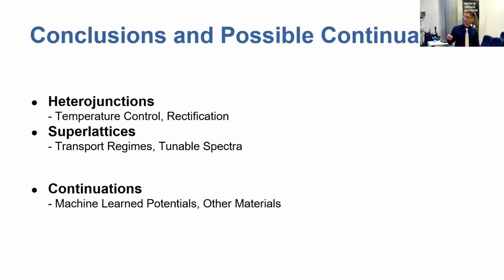Then we also described superlattices, which correspond to multiple interface structures. We have seen that in this case we can observe different phonon transport regimes, in particular the coherent phonon transport regime, which was not observed until superlattices became available. We can observe the coherent phonon transport regime only in superlattices, and we have also seen how superlattices provide us a viable means of tuning the phonon spectra of the material and controlling and engineering the thermal transport and electro-optical properties of a given material, or a given class or set of materials, as long as you can use them to arrange a superlattice.